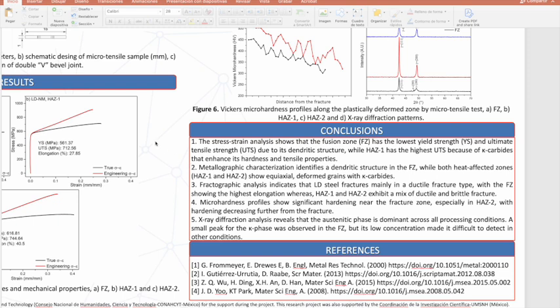Conclusions. Conclusion 1. The stress-strain analysis shows that the fusion zone has the lowest yield strength and ultimate tensile strength due to its dendritic structure, while HAZ1 has the highest ultimate tensile strength because of κ-carbides that enhance its hardness and tensile properties. Conclusion 2. Metallographic characterization identifies a dendritic structure in the fusion zone, while both heat-affected zones 1 and 2 show equiaxed and deformed grains with κ-carbides.